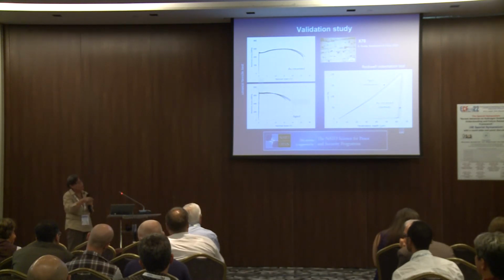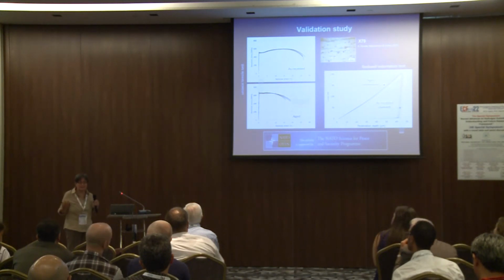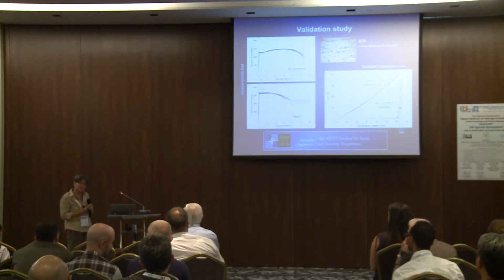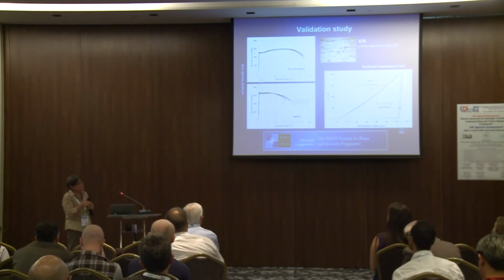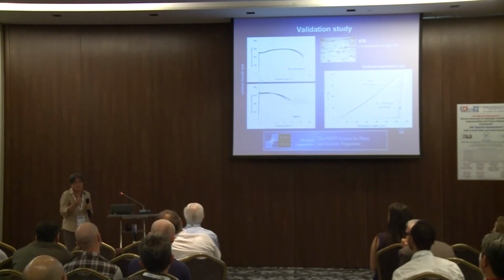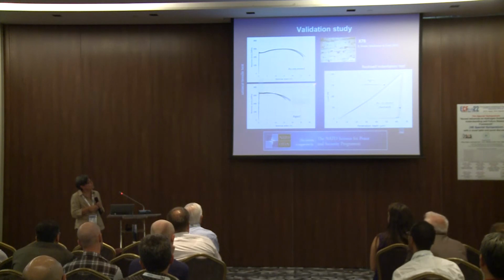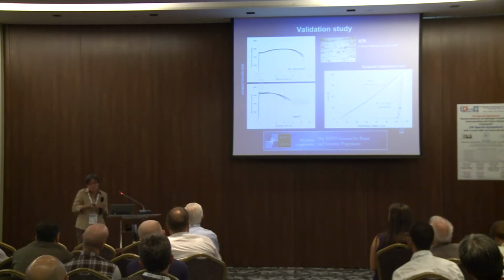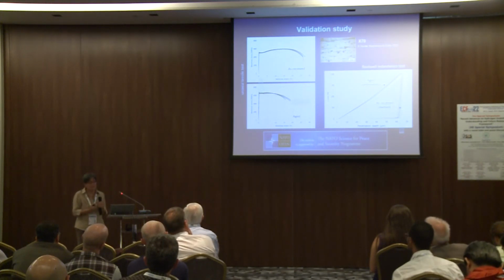Besides that, we are also, as I was saying, going to reduce the load very much compared to what is usually used in hardness testing. Therefore, in any situation where hardness tests are used, we are not doing anything more complex than that. And for this kind of material, this is fine. Again, I pointed out that the penetration depth is some 60 microns, which means that the overall depth of the material which may be really sensitive to this could be 0.2 millimeters, which, unless the material already has a visible problem, is not a reason for inducing defects. We also avoided, for instance, using Vickers indentation, which is pyramidal, which is used in different contexts. So with due careful approaches, I believe that is really safe.